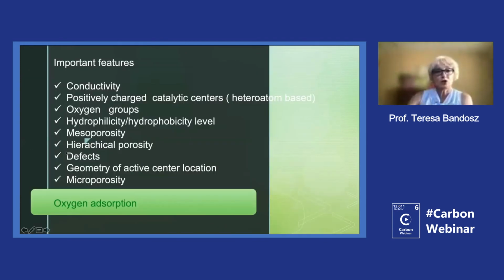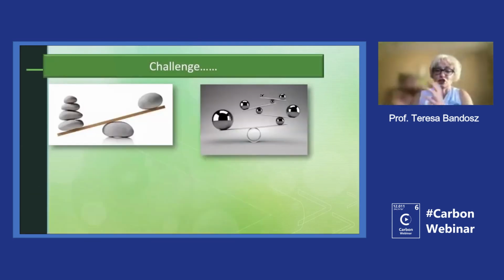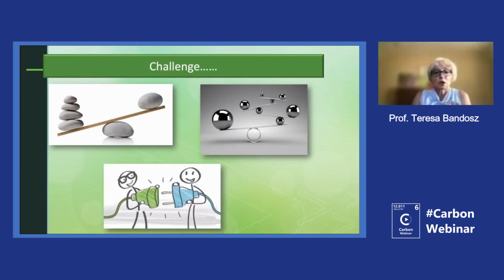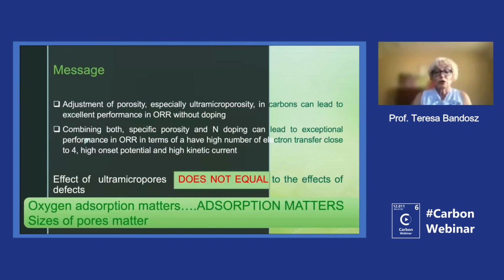So the important features on the surface of carbons, of course, there are many, and as I mentioned, some of them we are not really able to quantify well, but we think that oxygen adsorption is important, and the challenge is in the surface, because we have the pores and we have the chemistry. So how to combine it? It is not easy, because even though we are able to have the carbon, the graphene with chemistry, we are not able to have the pores in carbon without oxygen. Maybe, of course, the calculation would help in this case.